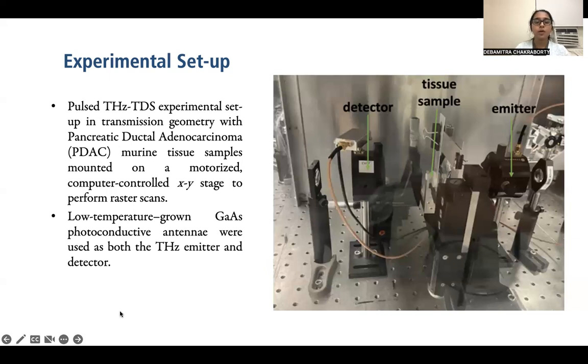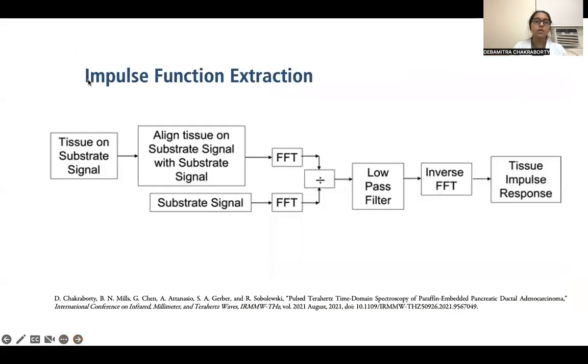The usual choice of substrate for biological tissue is glass, but we cannot use glass for terahertz time domain spectroscopy because glass heavily attenuates the terahertz wave. So here we tried different substrates and mounted the tissue onto them to look for the optimal one.